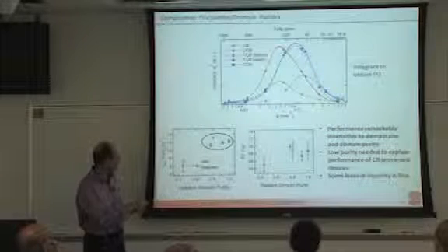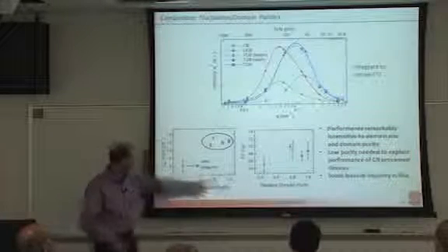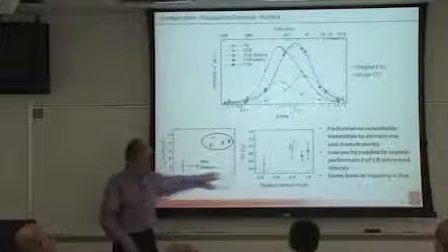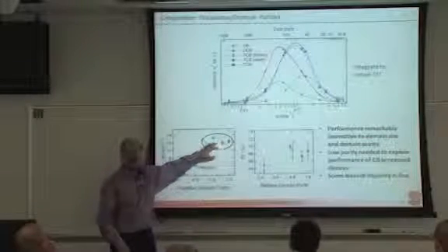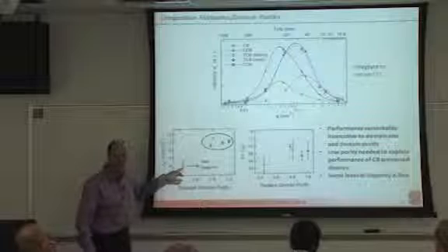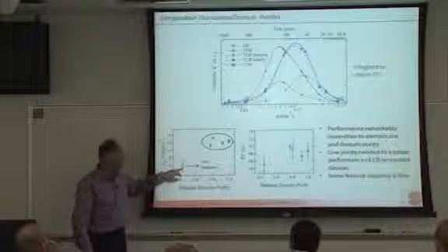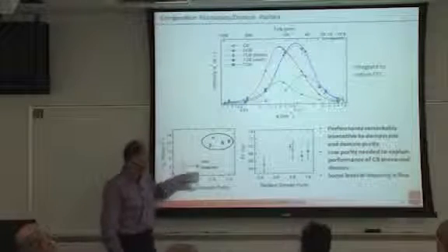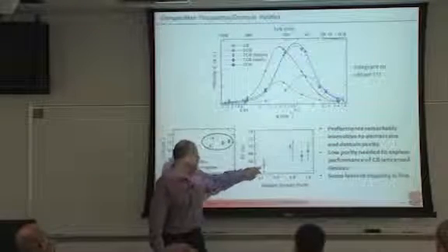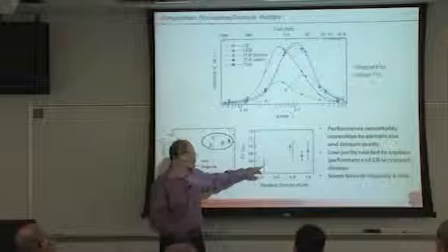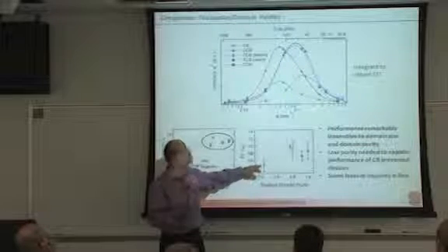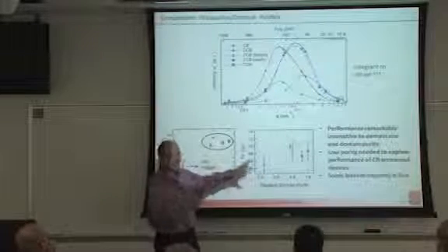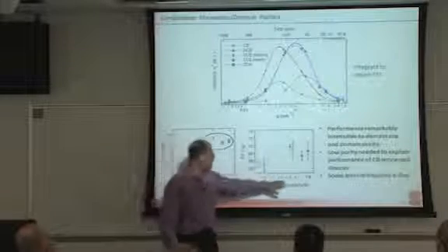And you find that the relative composition fluctuations over a 20% range have almost no impact on the performance. It's only when the composition fluctuations are very small, and that means the domains are very impure, that I take a hit. Strangely, the very impure domains correspond to small domains. It evaporates the fastest, so that's also clear why that happens.